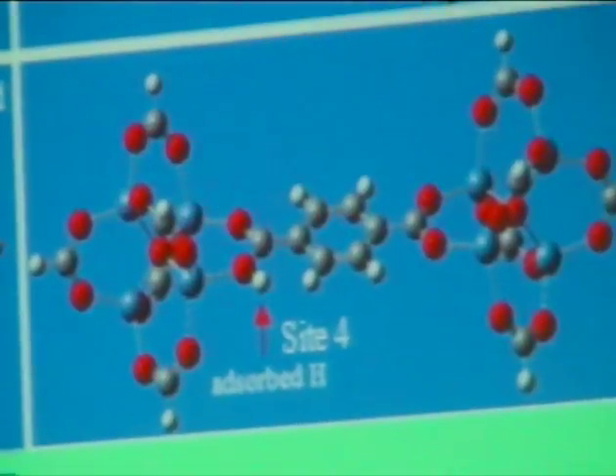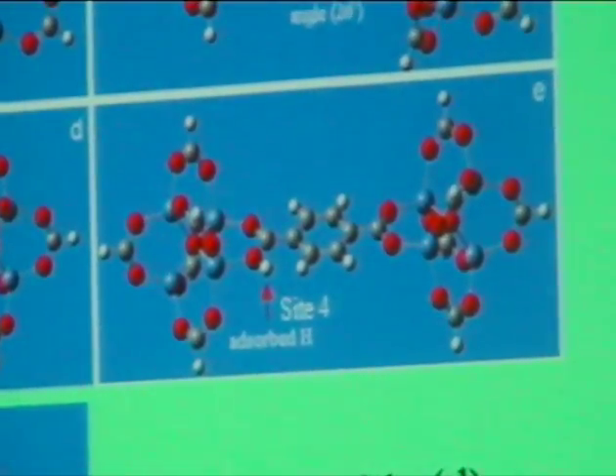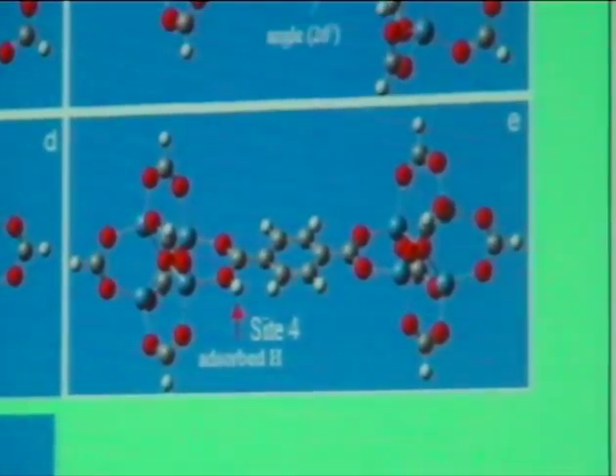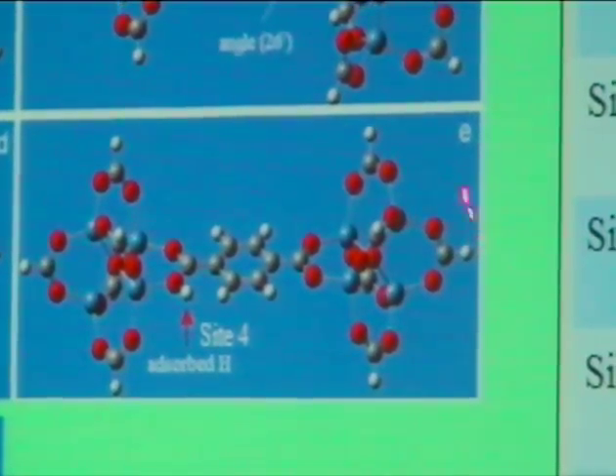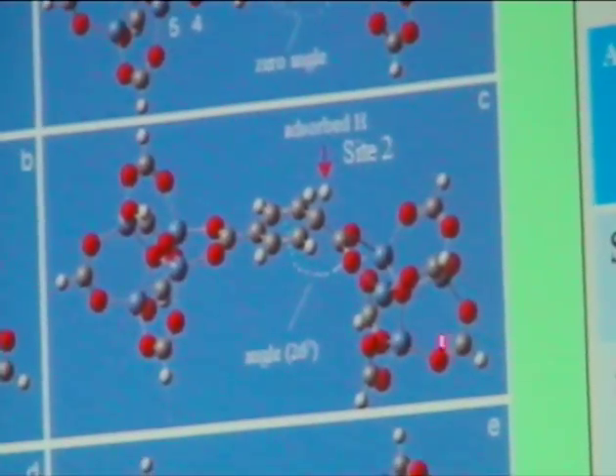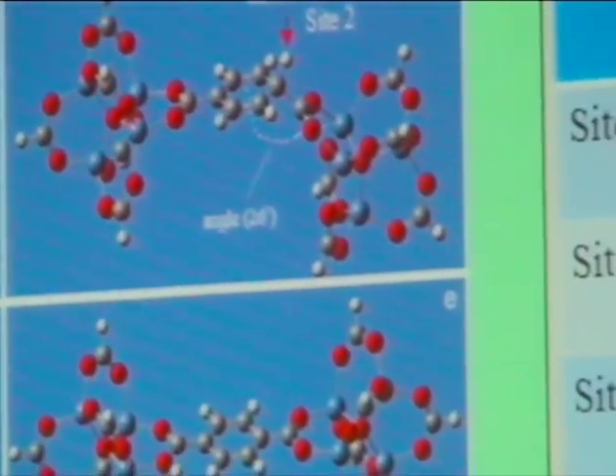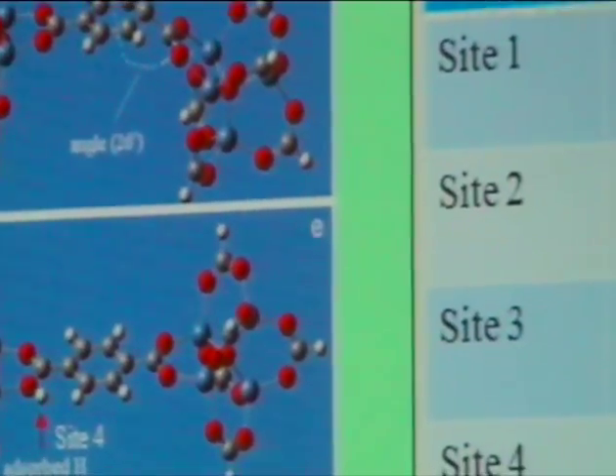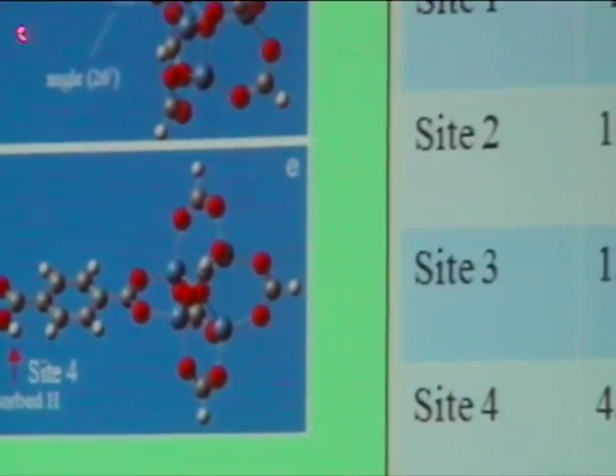But site 3 is good. Site 4 is 43 kilojoules per mole, which is higher than the 15 kilojoules per mole we need. And for 2 and 3, it is over 100 kilojoules per mole, so that's a stronger interaction. So the first thing we can say is that some active sites can strongly hold hydrogen. That's a confirmation. Most importantly, the DFT calculation shows you have the chance to get this hydrogen absorption, but you have to use experiments to confirm.